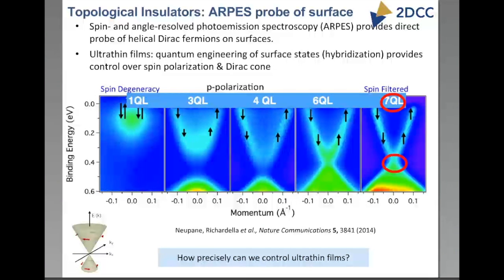Now, why is it that growing these samples by MBE is important? Well, because you can get new physics out of it. So this is an example of a technique known as angle-resolved photoemission spectroscopy. And in this case, it's also got spin resolution, which is shown schematically by the arrows on top of the plots. What this is showing you is the energy versus momentum, in other words, the band structure of bismuth selenide films of different thicknesses. The QL corresponds to quintuple layer. It's roughly about a nanometer.